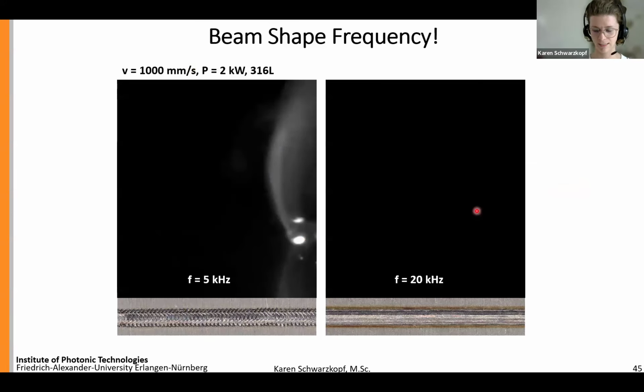Okay, so the next is more of a comment, which maybe you can talk about a bit if you want. So mentioning that also the beam shaping can be used to improve surface roughness and to minimize porosity in the deposit. So yeah, we could see an improvement of surface roughness in experiments that we conducted. Basically, what we did, we were employing a, let's say, polishing path to the part where we're employing a spiral again. And I tried to point out in my talk that the spiral really allows us to distribute the melt equally. And so we could see an improvement of the surface roughness by having a spiral beam profile used in the end of our volumetric build-up.